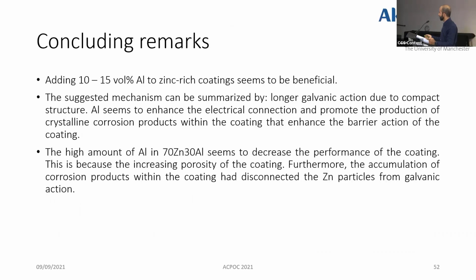preventing most of the zinc from galvanic action. So, the concluding remarks: adding 10 to 15 aluminum percent seems to be very beneficial in zinc-rich organic coatings, and the suggested mechanism is longer galvanic action due to compact structure, and aluminum seems to enhance electrical connection and promote the production of crystalline corrosion products.